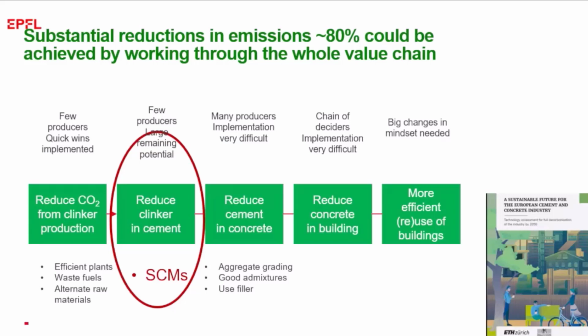Reducing CO2 from clinker production has already been largely achieved. The quick wins have been implemented. We can still go somewhat further by having efficient plants, using alternative fuels and raw materials. In the clinker and the cement, we can go further by increasing the amounts of SCMs, which is really only possible by using calcined clays because slag and fly ash are already used up.